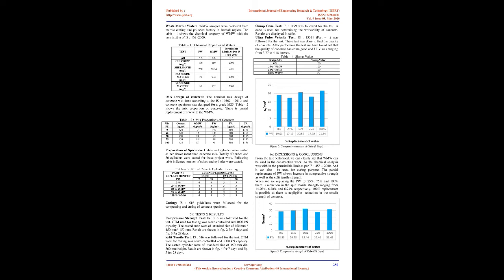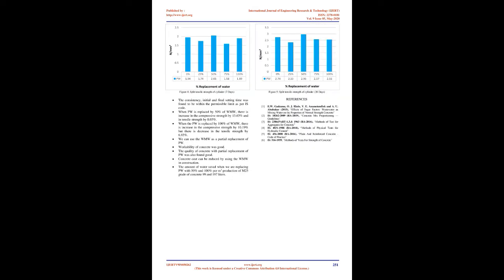5.0 Tests and results. Compressive strength test: IS 516 was followed for the test. The CTM used for testing was servo-controlled with 3000 kN capacity. The cast cubes were of standard size 150 mm * 150 mm * 150 mm. Results are shown in Figure 2 for 7 days and Figure 3 for 28 days. Split tensile test: IS 516 was followed for the test. The CTM used for testing was servo-controlled with 3000 kN capacity. The cast cylinders were of standard size 150 mm diameter and 300 mm height. Results are shown in Figure 4 for 7 days and Figure 5 for 28 days.